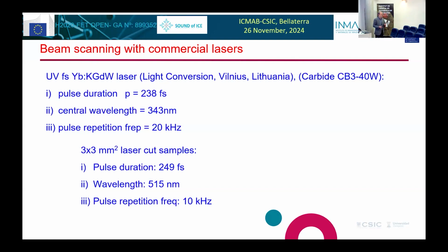basically, because it's well below the electron-phonon interaction, which takes place in metals, usually around 1 to 5 picoseconds time. So we are well below. So with each pulse, we don't get much thermal transfer at all with the excitation of electrons. But if we use very high repetition rates, then heat accumulates. So then we have a problem with heat. So we try to avoid the problem of heat by working at low frequencies.